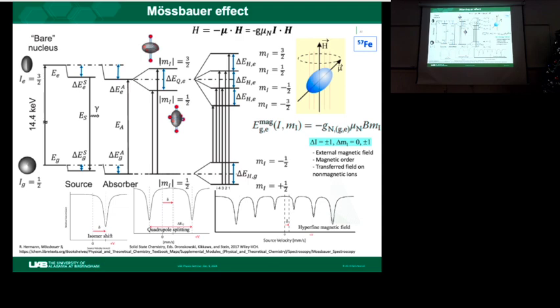And also another parameter called quadrupole splitting, and this terminology is specific to iron, but it basically can also tell the crystal structure transition when you have a different distribution of electric field gradient around the nucleus that also shows up in this quadrupole splitting parameter. And of course, when you have a hyperfine magnetic field around the nucleus, that also shows up in the nuclear Zeeman splitting. And then based on these different types of interactions, you can get a picture of what's going on with the electronic environment.